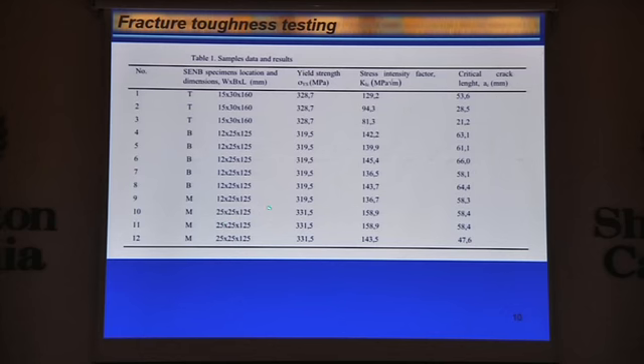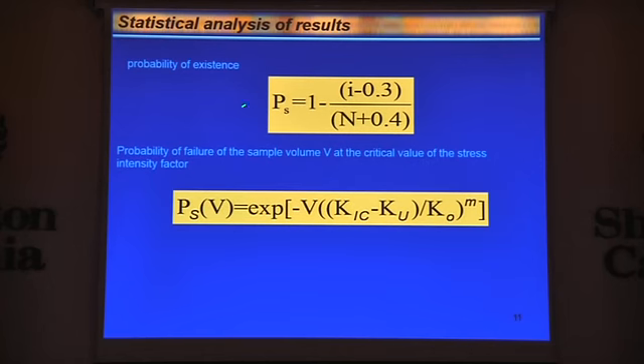We have from this area values like yield strength, and for each of these specimens we measured the fracture toughness values. Also, using the formula for linear elastic conditions, we can assume the critical crack length for this material. But in order to get reliable results, we should apply some statistics.